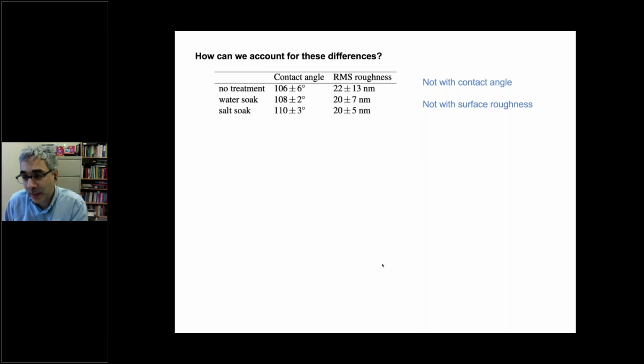Well, to return back to what I was telling you about contact angle, the first thing we did is we measured the contact angle quantitatively through a microscope, characterizing the shape of this droplet. And here we saw that in all cases, pristine silicone rubber, water soaked and salt soaked, we really see no difference at all in the contact angle. So this goes to show you that this is too macroscopic of a probe. So whatever happens to the silicone rubber, which makes the algae adhere more or less strongly, we really can't capture any of that with contact angle.